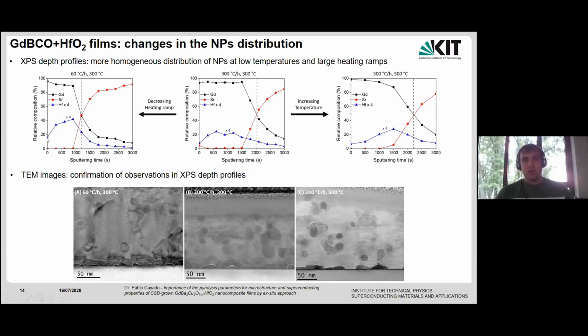We see that, for example, in this case, we see a tendency to agglomerate towards the interface, and also in this case, they tend to agglomerate toward the interface. While here in this middle sample, the signal is more or less stable, the concentration is more or less homogeneous, which means that we have less tendency to go to the interface. Also here, you see in these TEM images the confirmation of what I showed you here in the XPS. So at this 60 degrees per hour and this 500 degrees, we see a much larger amount of nanoparticles at the interface, as you can see. So much larger than here in the middle sample, which means that the GBCO has to nucleate on top of this. So the amount of misoriented grains is quite a bit larger.